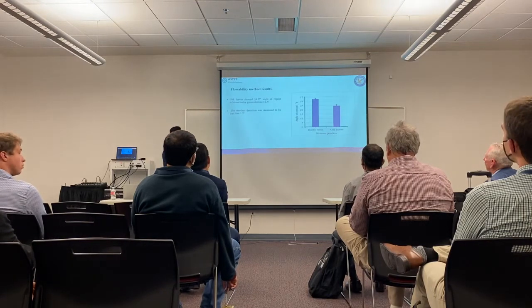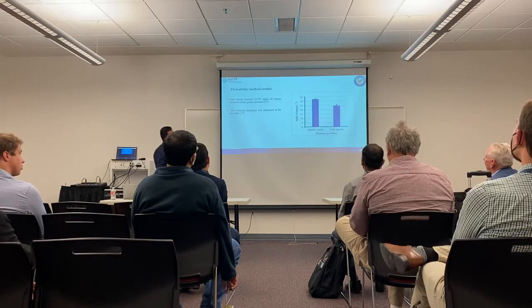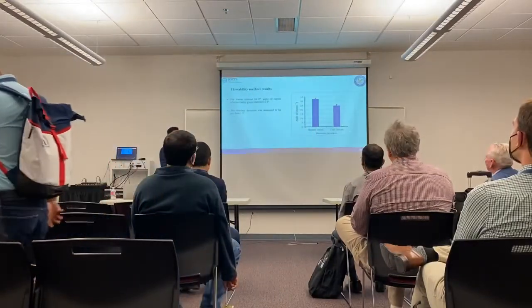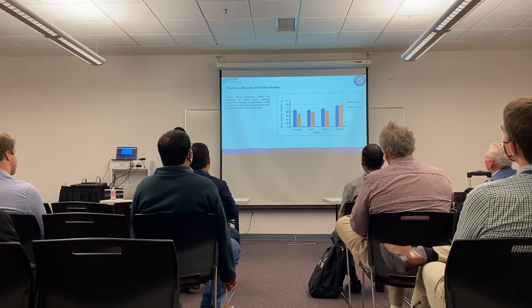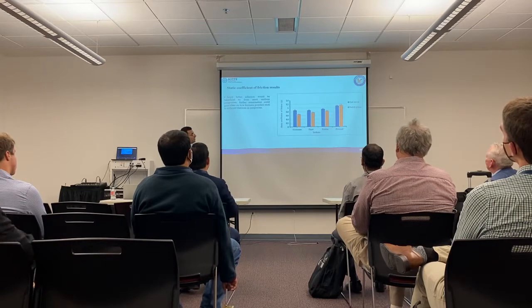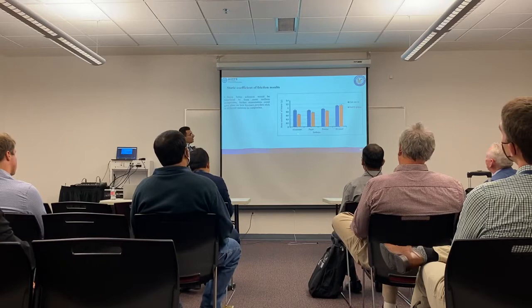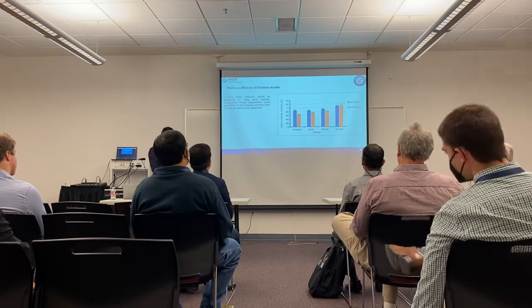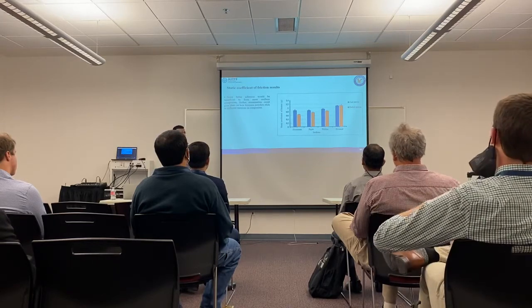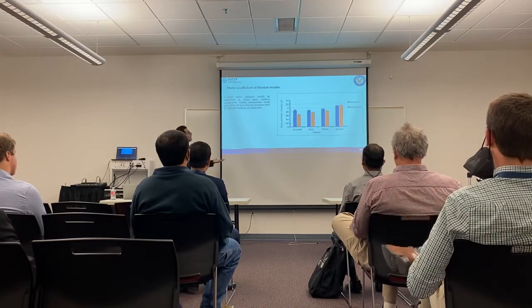And we have flowability. We could see that the oak leaf has excellent flowability, better than barley seeds, due to the lower angle of repose. And here, the highest static coefficient of friction was on the plywood surface, and the lowest static coefficient of friction was on the aluminum and paper surfaces. And, for example, further examination could give an idea of how biomass powders stick.